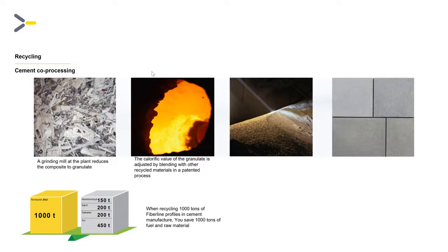This is very hard to use on the large wind turbine blades, because they have a lot of other materials than glass and resins. They also have a huge amount of balsa wood. They have carbon fibers. They have wiring and lightning conductors as well, which is actually not good when you manufacture cement. You need to know what is in the ovens, what is rotating over there.